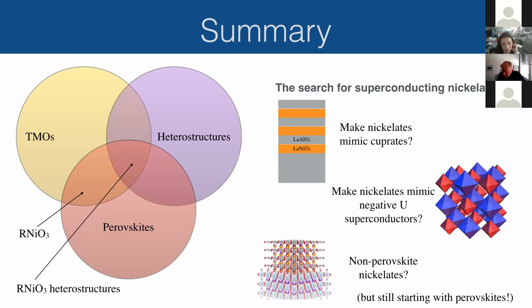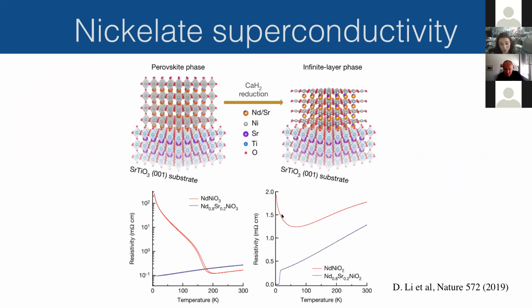Yeah, so in the first paper where they reported the superconductivity, they already noted this. So, for example, the parent compound of the cuprates, when you don't dope them, so they're not superconductors, tends to be antiferromagnetic, an antiferromagnetic insulator. But the parent compound of the infinite layer nickelates, meaning the neodymium nickel O2, so without any strontium doping, is not magnetic according to neutron diffraction measurements, and it's not really insulating, although it has this upturn. I can show you the data. I think I can show you the data again. It has this upturn. So already they were thinking that it's not really that similar.